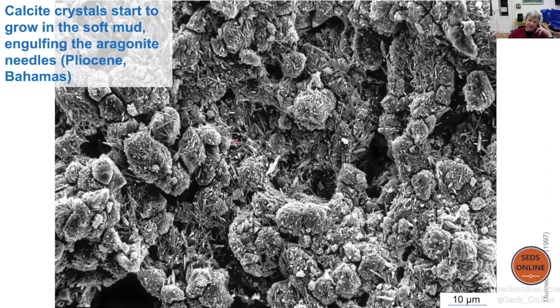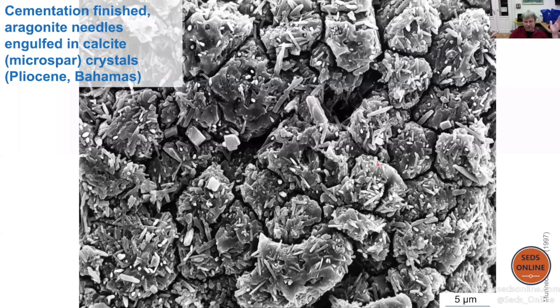Okay. And this is a weakly lithified sediment from the Clino core, and it looks a bit clotted. And if we look at these clots, we still see the aragonite needles. And actually these clots are calcite crystals. So inside of this fluffy, water-filled, aragonite-dominated needle mud, calcite crystals start to grow, and they grow bigger than the aragonite needles, which means the aragonite needles are incorporated in the growing calcite crystals, poikilotopically or poikilitically. And this continues until these crystals reach each other. So now the cementation is completed. The crystals cannot grow any further because they reach each other. But we see the aragonite needles, they are all sticking inside these calcitic crystals. And this already resembles our microspar.